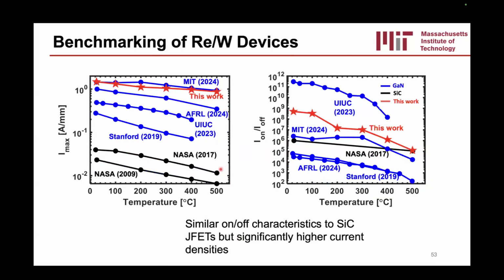All right, and we can benchmark this device against other devices in the literature. Once again, we get very high current densities because of the scaling. And we're able to get a relatively good on-off ratio of about 10 to the 6, which is pretty much identical to what the state-of-the-art silicon carbide devices see at these high temperatures. But once again, we get significantly higher, about 2 to 3 orders of magnitude higher, current densities.